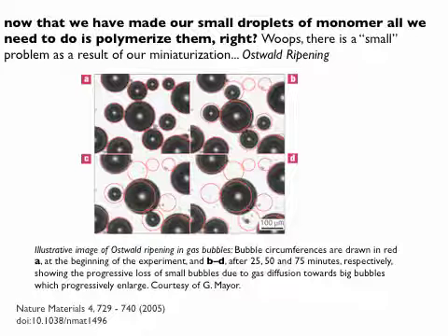If you're a large droplet, then the number of molecules that are on the interface with respect to the ones that are in the bulk is way less. So the fraction that has a tension is way less. So as a result of that, that system is a bit more stable. So that is how you could, in a way, qualitatively think about Ostwald ripening.